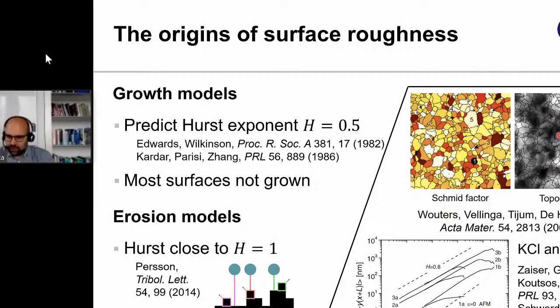On the other hand, there's some very interesting work now on single crystalline materials. The material microstructure, of course, represents material heterogeneity. What you see down here is the autocorrelation function of a surface scan, an experimental work out of Michael Zeiser's group, who's now in Erlangen, from the compression of single crystalline potassium chloride and lithium fluoride samples. You see that on these single crystalline samples without any heterogeneity, you also find surface roughness after deformation that is self-affine. In this case, the scaling exponent or Hurst exponent is close to 0.8.